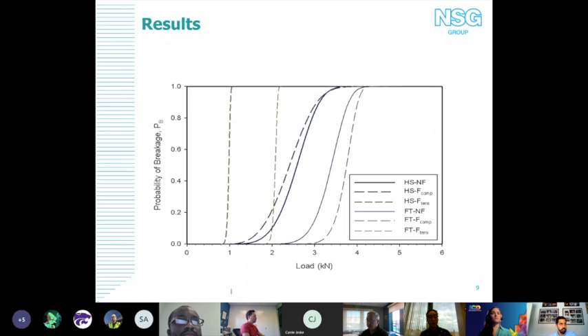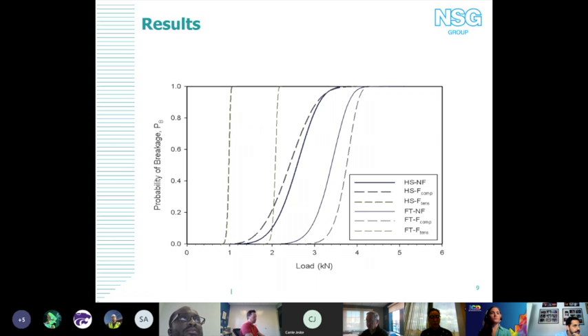So next slide. Yeah, so here we see just a general layout of our load at failure, or our 3-second equivalent failure load, and our probability of breakage. So we're going to focus down towards the bottom, but looking at a general rule, you see that your control and when frit is in compression have fairly similar failure distributions, at least in terms of the coefficient of variance. You see a similar trend, and